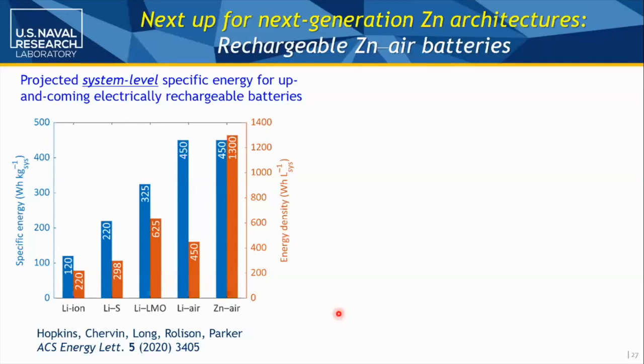Now we've got to do work on the cathodes. So Brandon went back into the literature with everyone's projected practical specific energy or energy density for state-of-the-art lithium ion, lithium sulfur, the approach to go to layered metal oxides versus lithium metal, the Argonne estimate of the best number you might get out of lithium air, and then zinc air. And of course, these orange ones are what we care about. It's that energy density. And of course, zinc is known for good volumetric energy, and lithium is known to be very bad with respect to that. So why are we putting quite so much effort into lithium?